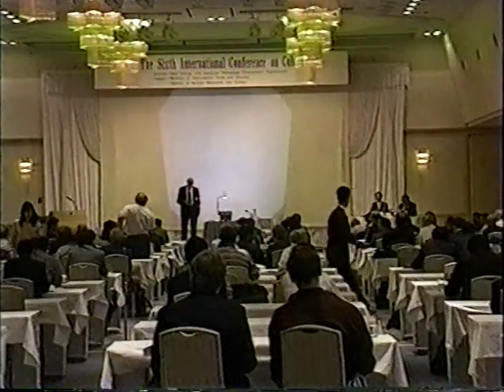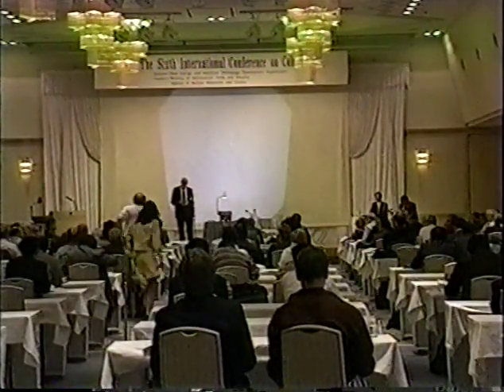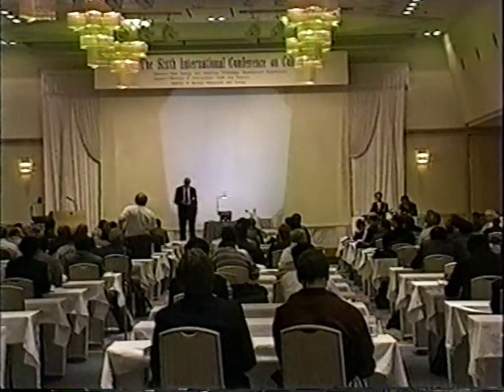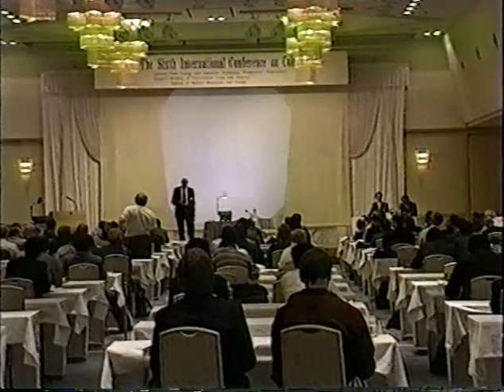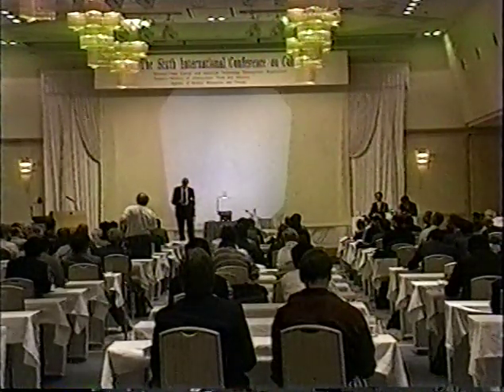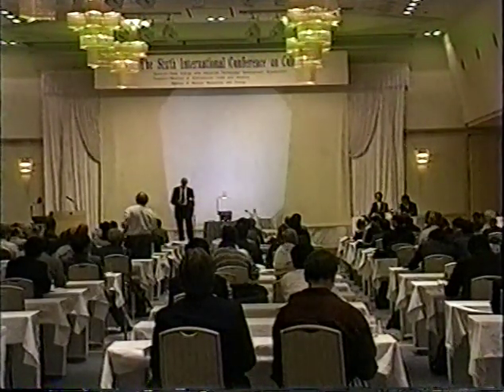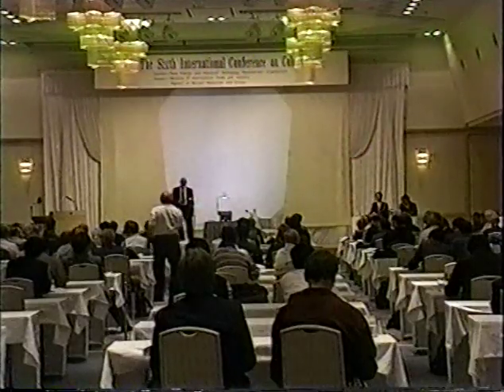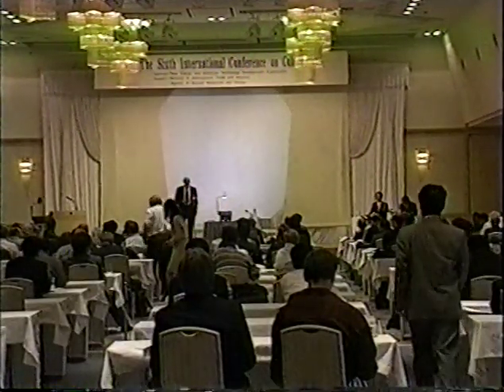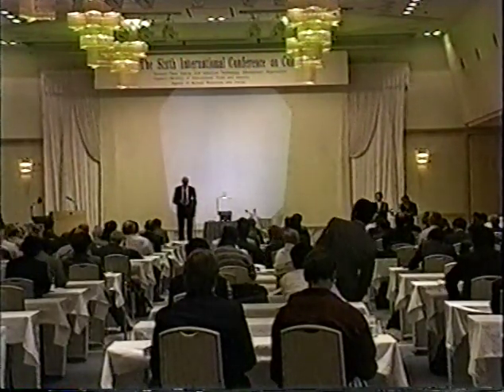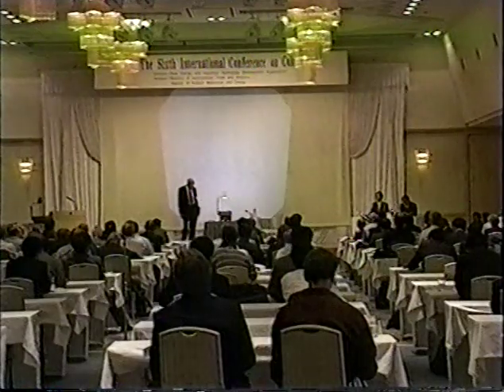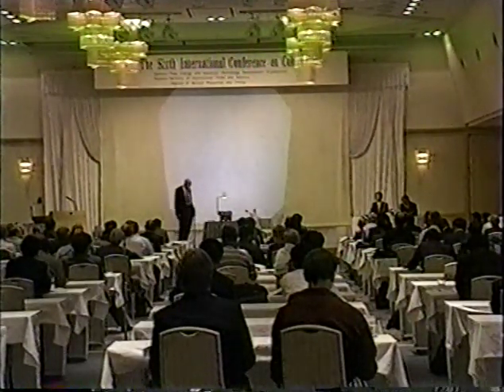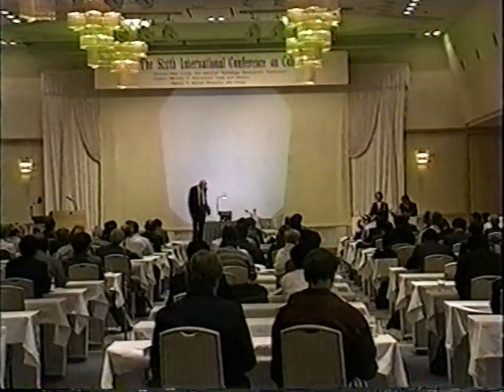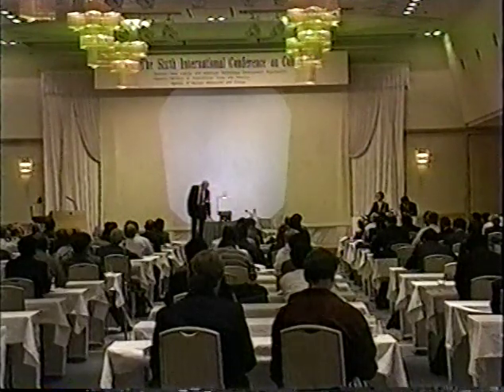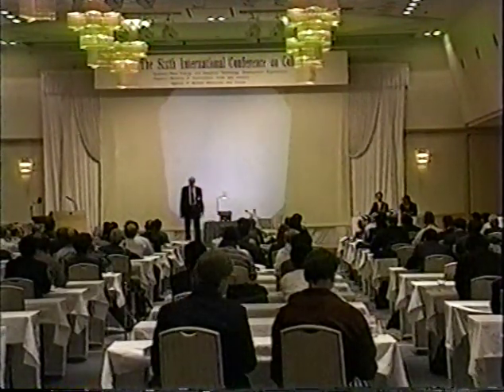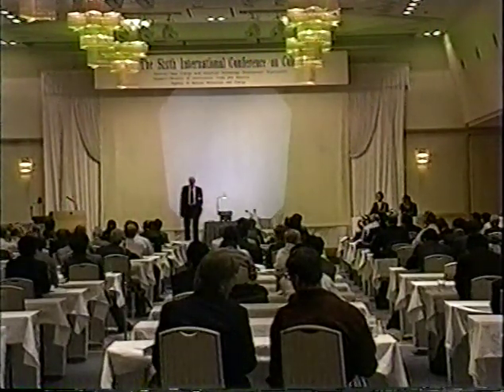There's always the worry about leaching, but you might be interested that there was quite an interest in making palladium-boron diffusion tubes, including palladium-boron diffusion instead of palladium-silver for electrolyzers. So it certainly doesn't come out there. It's stable. Well, I hope that's true, and I thought I'd better check it, though, because it's a pretty amazing result if it is indeed confirmed. And of course, if boron can do it, many other things perhaps can do it as well, and so we shouldn't restrict ourselves to looking at this one. It just happened to be convenient to look for based on the fact that boron-10 has a 4,000 barn cross-section. And even if it has 100 parts per million, I can readily see it.